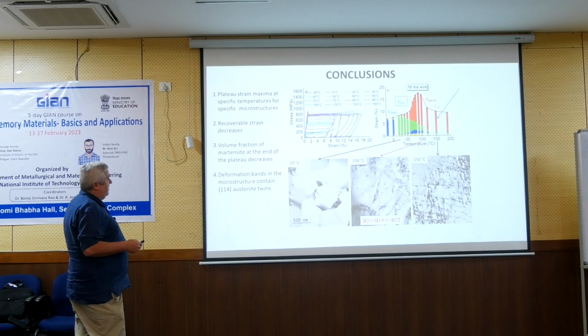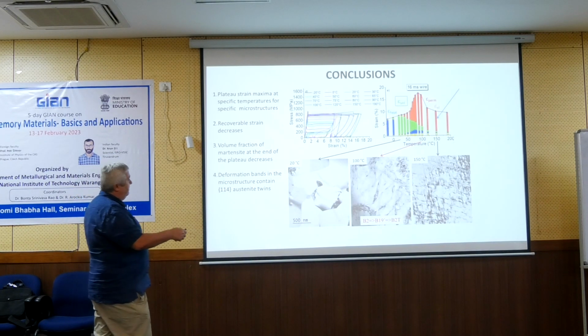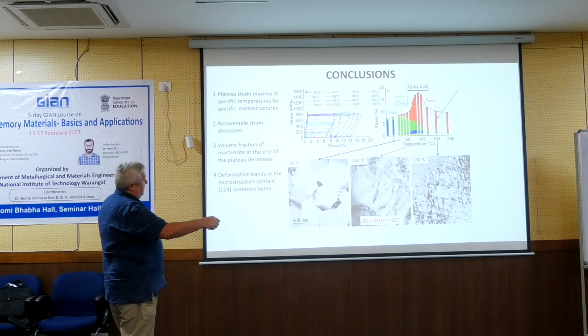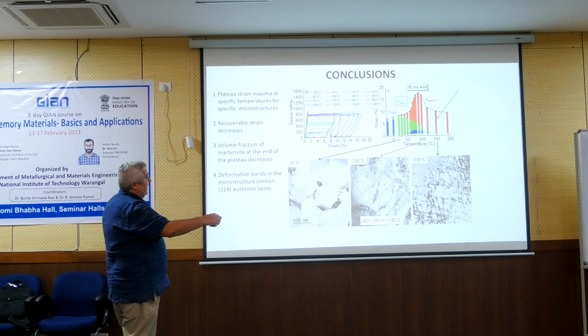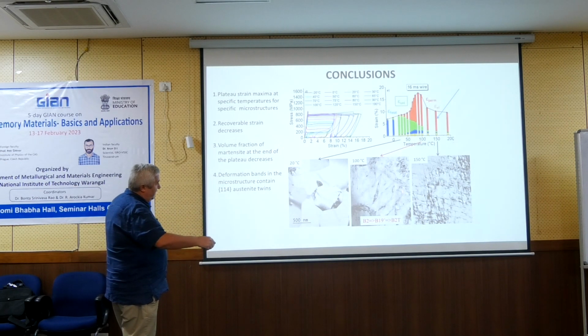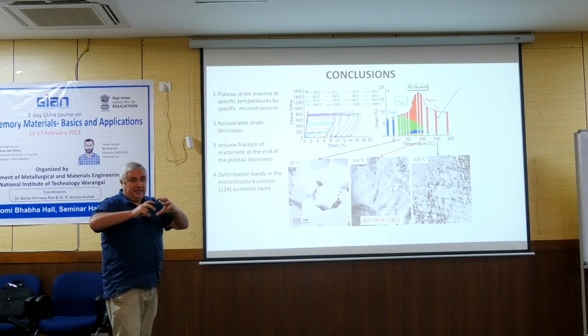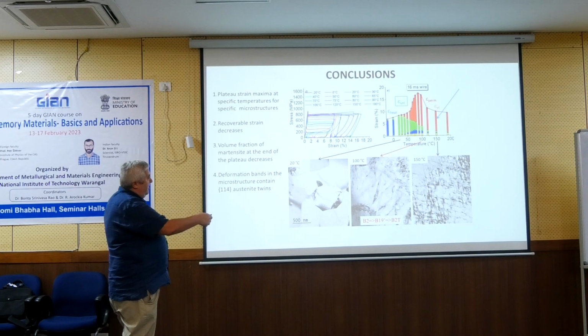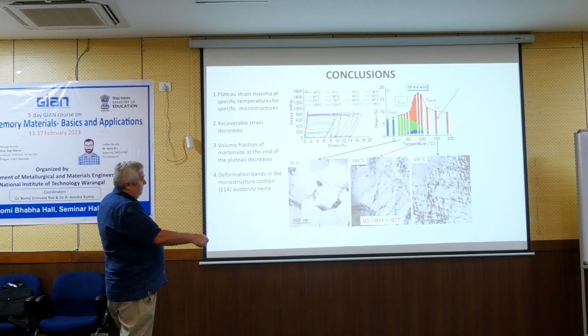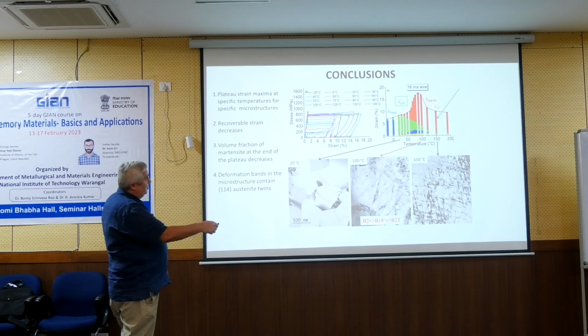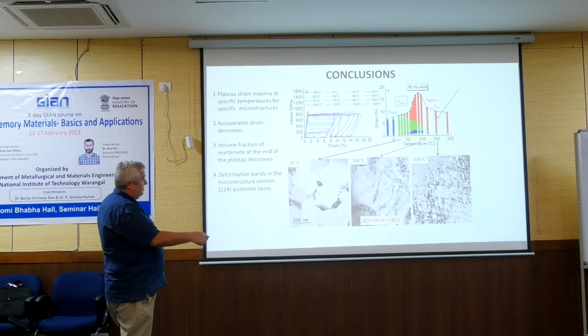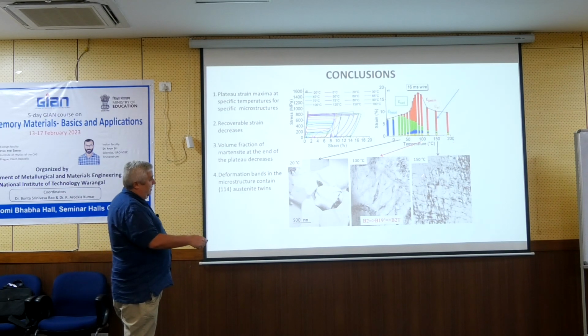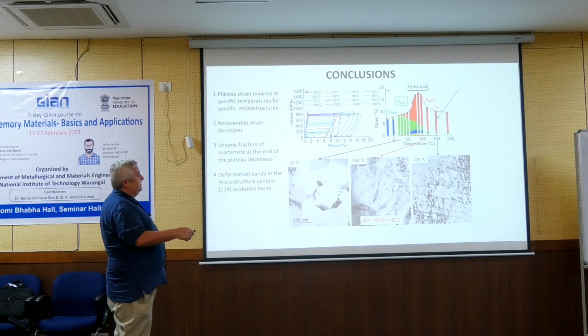This is basically the same as what I said. The main thing to remember is that the plateau strain is definitely not constant. It can change at high temperatures around 100 degrees. It can increase, but the increase is due to this twinning mechanism, which is related to the reorientation of the austenite lattice underneath. And at still higher temperature, you don't have it. If you don't have it, you have a lot of slip. The reason for this decrease is that this process of twinning is not so active, and you have normal twinning in martensite or austenite, we don't know, but as a result the plateau length is short.